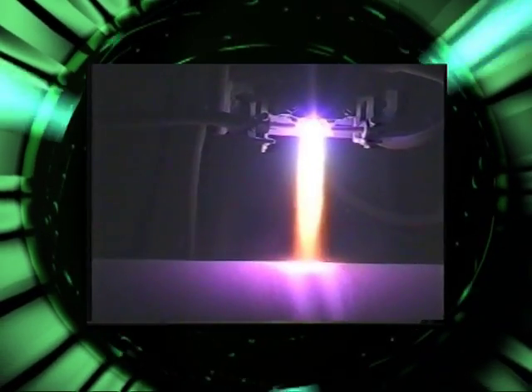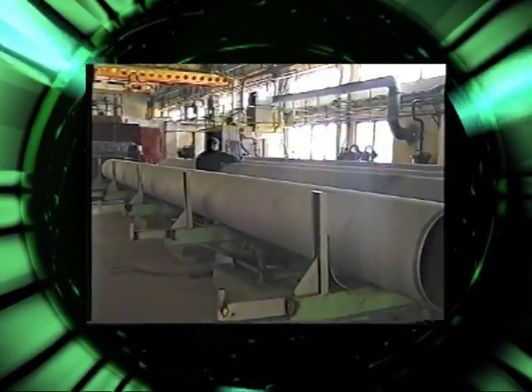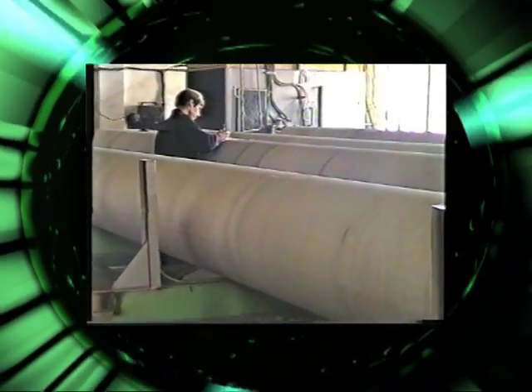Being deposited on the weld, the coating does not only protect a weld against corrosion, but also imparts to the weldment high resistance to corrosion fatigue crack initiation, including cracks initiating in the fusion zone under repeated static loading. The aluminum-ceramic coating protects also the regions having a partly peeled coating. It does not require further impregnation and is superior to the aluminum one in corrosion and wear resistance. Steel sheets with the coating are suitable for cold forming and rolling without worsening of their coating protective properties.